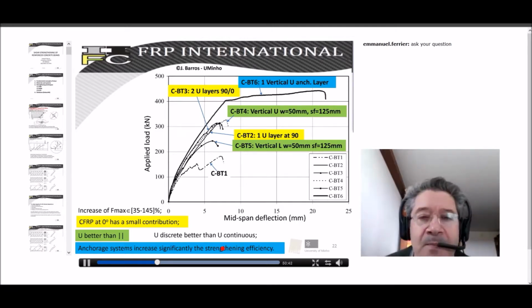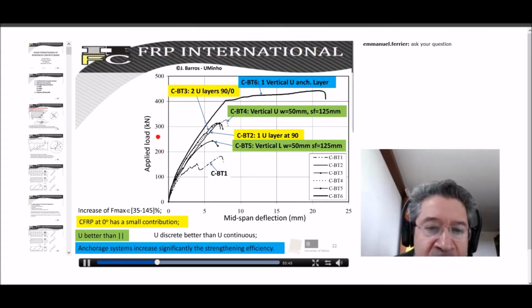We have here the relationship between the applied load and the mid-span deflection. The first aspect, which is quite clear, is when we compare the force-deflection relationship obtained in the reference beam, where we don't have any type of shear strengthening system. So this is the maximum load. For the other types of beams, we realize that we obtain a significant increase in terms of ultimate load. The increase is between 35% and 145%.